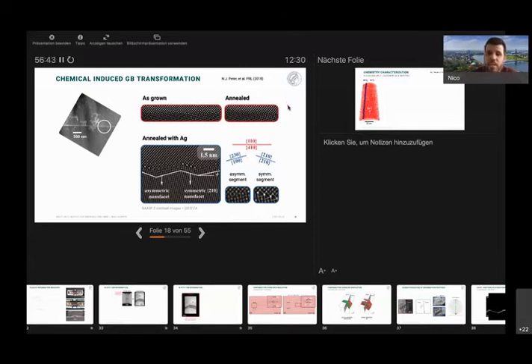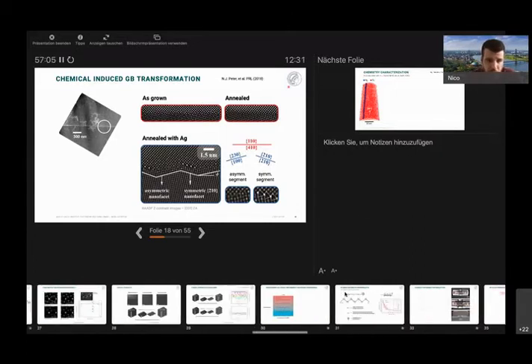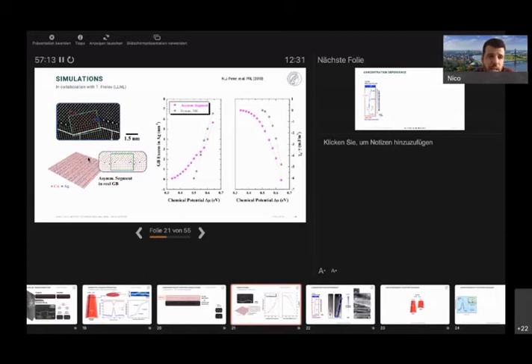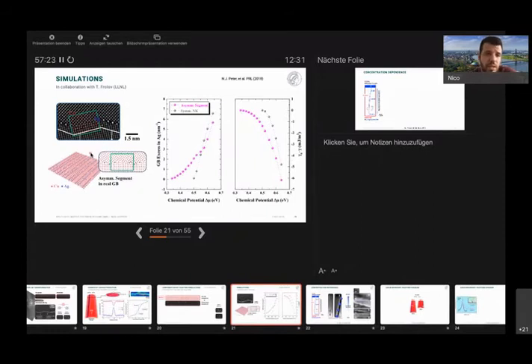That could be, that might be, if you have a very, very big atom. But the Z number of silver is, I think, 47, and copper is 29. So if you go to really big atoms, maybe gold, but I think for gold, it has also been shown that it goes to these positions. However, really not so many people look at the asymmetric boundary. So it could be that the behavior of the boundary that I showed in this slide, that it forms these extended segregation patterns, like line segregation patterns, could be different for different elements. That I don't know. That would be probably interesting to look into. We didn't go further into this so much. But then your question is more related towards the preferential segregation. Is that changing? Maybe, and that could indeed be a function of the solute.